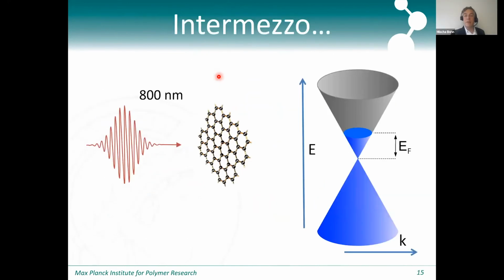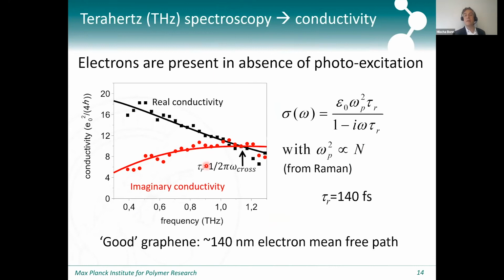All right, so let me try to continue. And so this is just to illustrate the strength of this technique for characterizing charge carriers. So you have to realize that this is not a large density, right? It's 10 to the 12th per square centimeter. It's not a large density of charge carriers in the material. The charge carriers that are there are very conductive, so they have a very long mean free path or a long scattering time. But it's only one layer of material that we're looking at. And so we clearly have the sensitivity to characterize that one single conducting layer quite nicely.